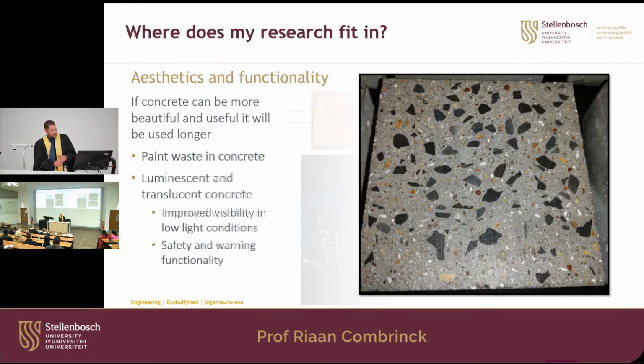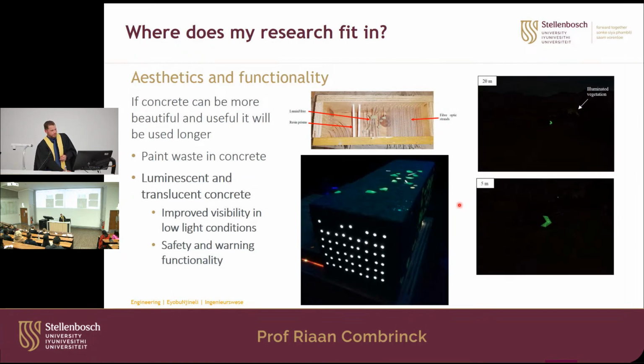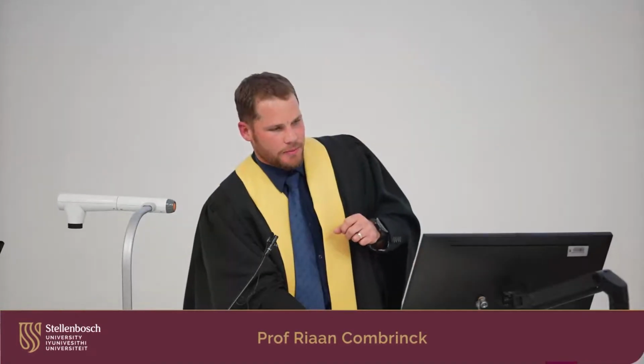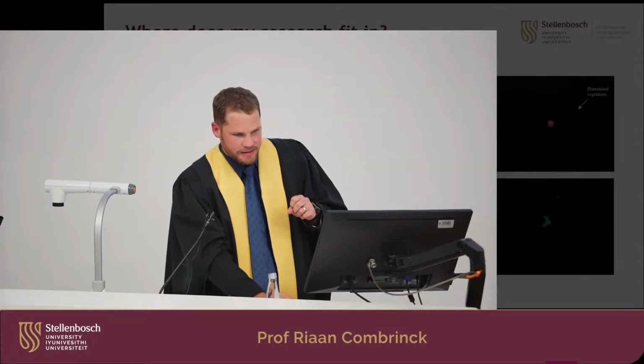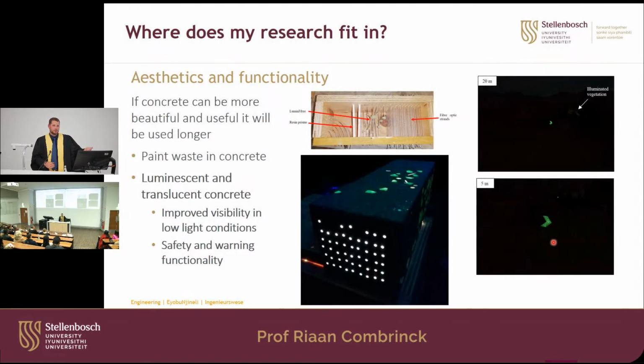Then also translucent or luminescent concrete. So this is for improved visibility in low light conditions, and also safety and warning functionality. So we added fiber optics to the concrete, and then if load shedding would happen now, we have a glow-in-the-dark aggregate in that wall that charged from the outside, and if load shedding goes off, we can hopefully see, because now it's emitting its light in here. So some of that type of functionality, and even using it as signs. This is a traffic sign we erected, and it can charge via the sunlight or maybe the lights of your car, and then it emits this light that you can actually see when there is no light.